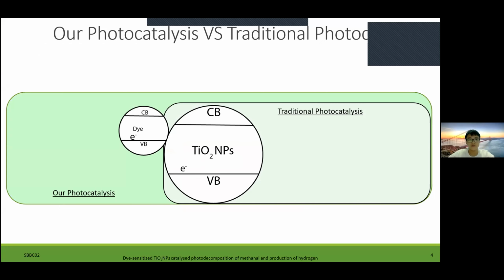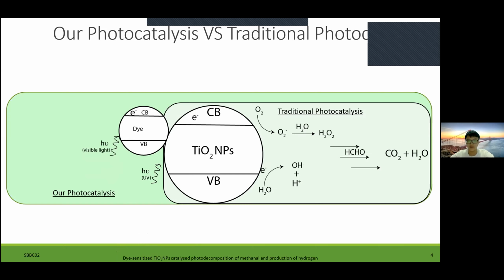So here you can see, both the dye and titanium dioxide nanoparticles are photoexcited by visible light and UV light respectively. This generates an electron hole pair and allows oxidants, such as superoxide ions and hydroxyl radicals, to oxidize methanol. And in our improved photocatalysis method, the photoexcited electron of dye can be transferred to the conduction band of the titanium dioxide nanoparticles. This oxidizes the dye and it can act as an oxidizing agent of methanol as well.